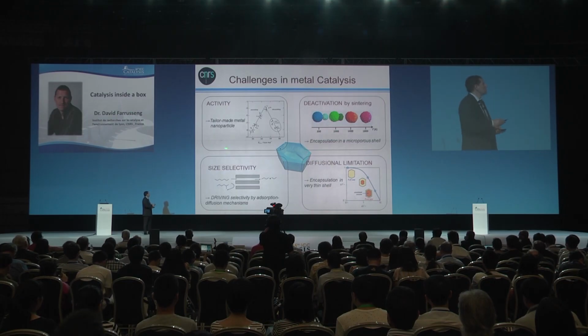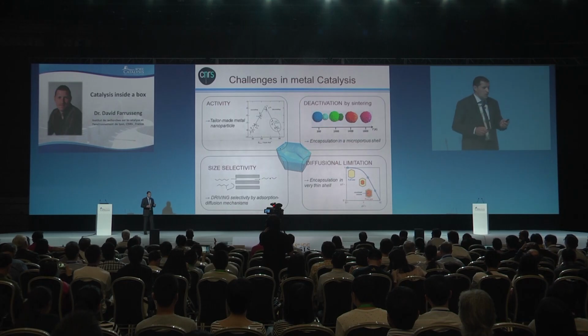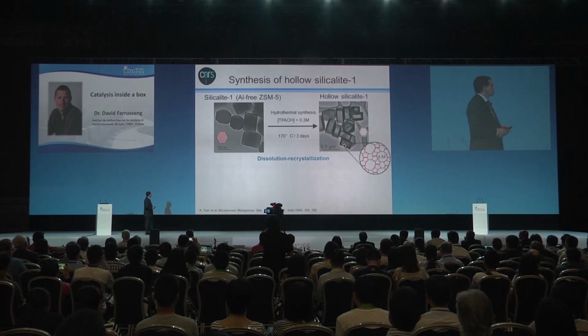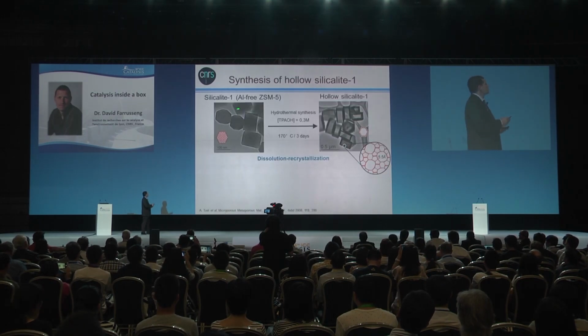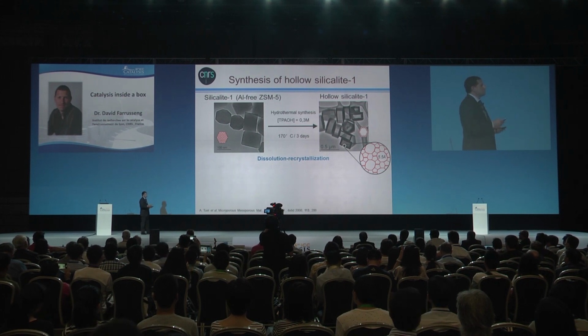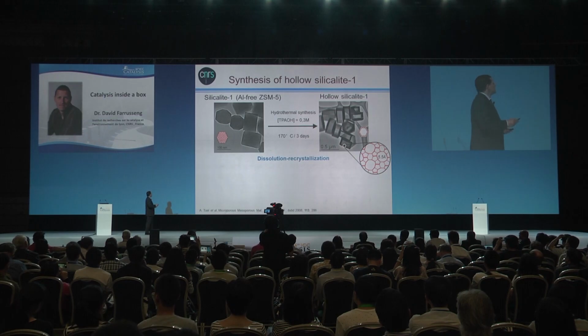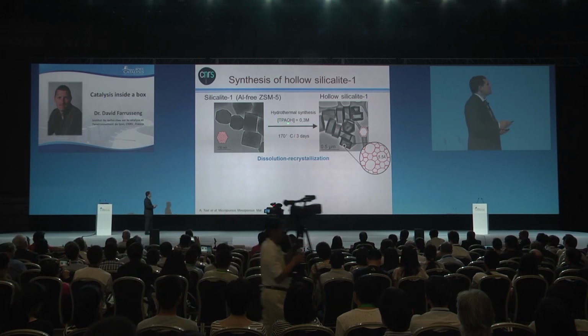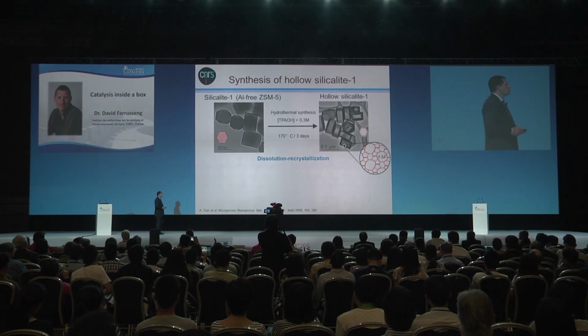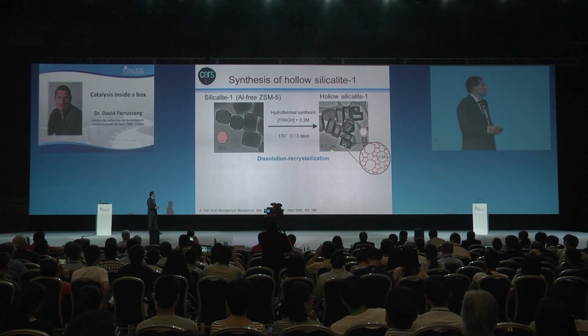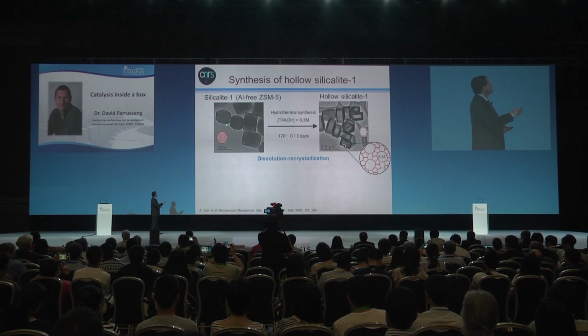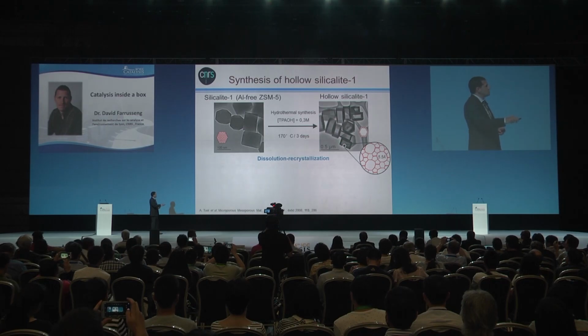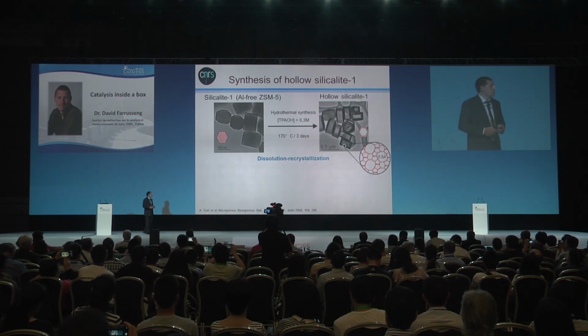But before addressing the activity, I want to show how we make these hollow zeolites, like that. It's in fact very simple. You start with silicalite 1 crystals, if you wish, aluminum-free ZSM5, and then you treat them in the TPAOH, so tetrapropylammonium hydroxide solution at high concentration for 3 days, and you're gonna see these hollow crystals. You can recognize here the hexagonal shape. This is the top view, you have it here, and the square shape, this is the side view here. And every one of them is hollow.